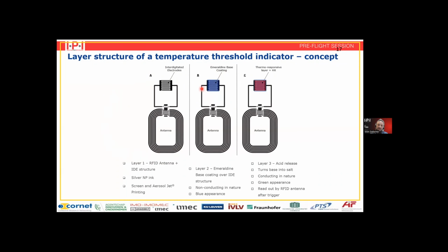So, this base coating is a coating that is, let's say, non-conductive. But at the moment that a specific temperature is reached, you can create a release of a specific acid. That's the idea that we had here, the acid release, such that this emeraldine coating becomes conductive. And then, of course, you have an interconnection, and the antenna RFID system will sense that the temperature threshold is overcome. So that's the idea of the complete design.